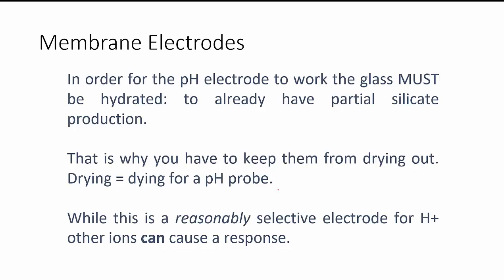In order for the pH electrode to work, the glass must be hydrated. All right, so remember this, it must be hydrated. If I'm ever on you guys about, hey, don't let your pH probe dry out. Drying is dying. This is why. It needs that hydrated gel layer. If your pH electrode membrane dries out, it's not going to work anymore. Right? You also have to have partial silicate production. That's why you have to keep them from drying out. This is a reasonably selective electrode for H+. Other ions can cause a response. I remember I said we could trick this electrode.